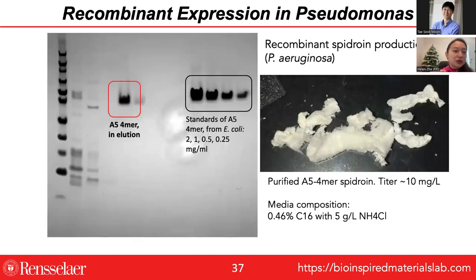We also were able to create silk. So in the same strategy, we integrated into the genome the gene for creating our A5 4mer spidroin. And using hexadecane as a sole carbon source, our Pseudomonas strain was able to create about 10 mg per liter of this silk protein, which you can see right here. And it can do so with about 0.5% C16 and a little bit of a nitrogen supplement.